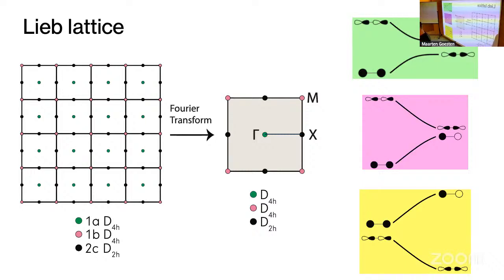This is also not enough, okay? And this is actually very chemical, because if you only control, let's say we put a p orbital here and an s orbital here, what we also need to control is the energies of the orbitals. So this is real chemistry. Let's say we have three scenarios. I showed you this avoided crossing a few slides ago, where this is an s orbital and this turns into a p orbital because we have a non-trivial gap. But we can also have a situation where these two are so far separated in energy that they actually do not cross. So this is a topologically different scenario, okay? And actually the outcome here is pure chemistry, which determines that, the chemical bonding property.